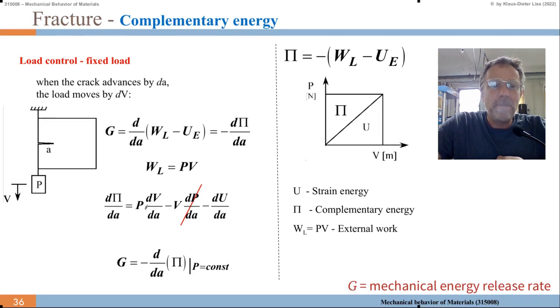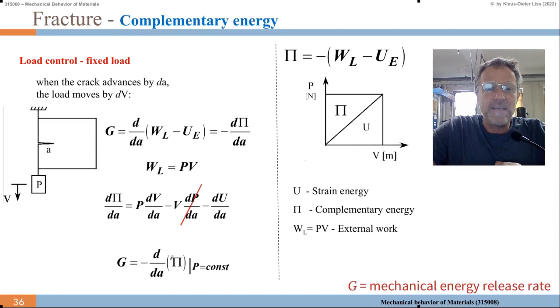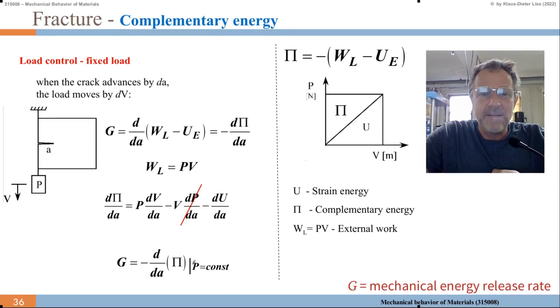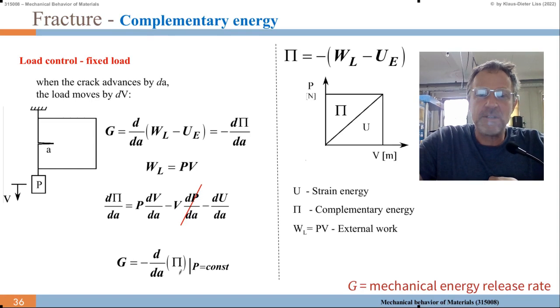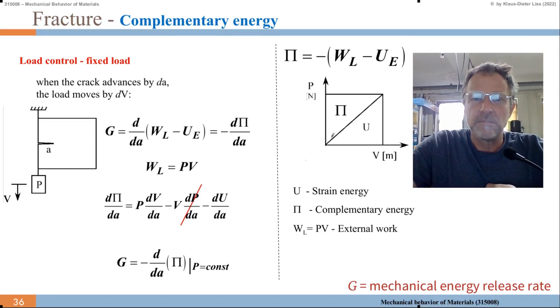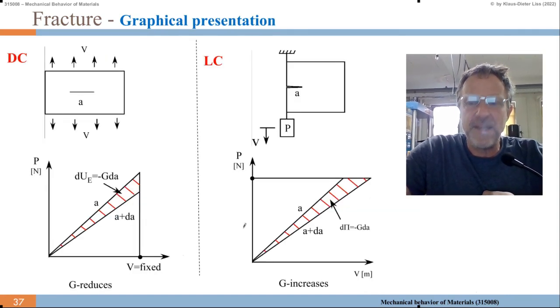So d pi over dA equals P dV over dA minus V dP over dA, which is zero because we keep P constant, minus dU over dA. That gives us the strain energy release rate equals minus d over dA of pi, at P equals constant. So that's the change here.